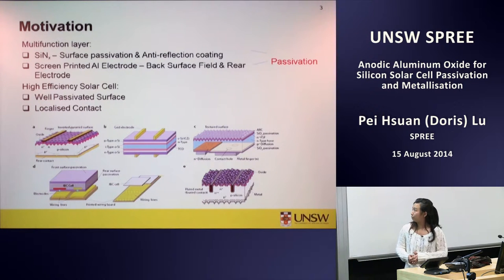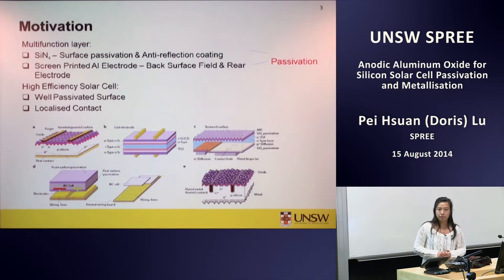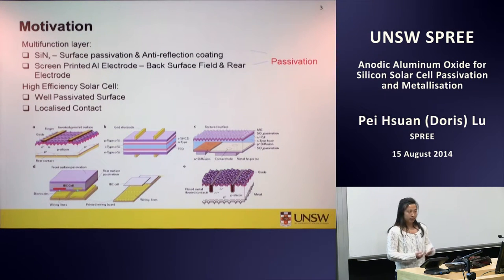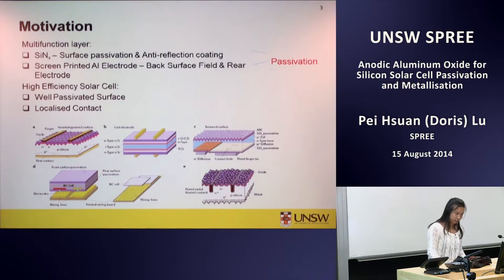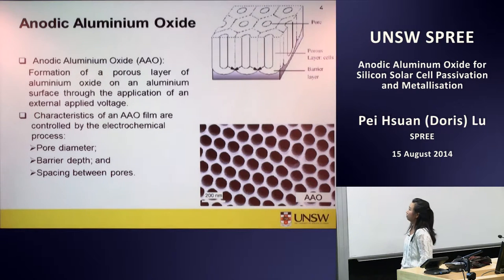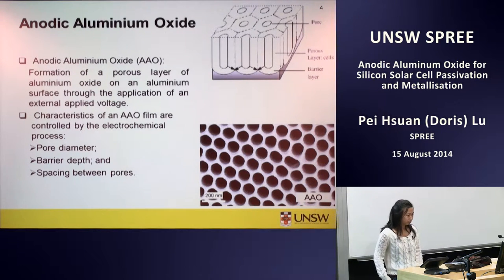Try to reduce the recombination at the localized area and passivate the surface region to reduce the surface recombination velocity. So to further improve the commercial silicon solar cells efficiency, it will be sensible to achieve a way to passivate rear surface and form localized contact in a commercially viable way. That's when we kind of propose anodic aluminium oxide.